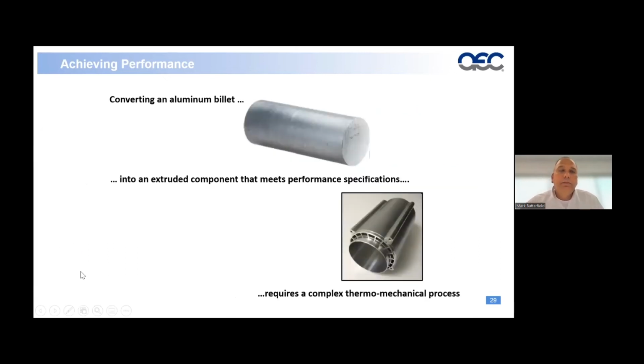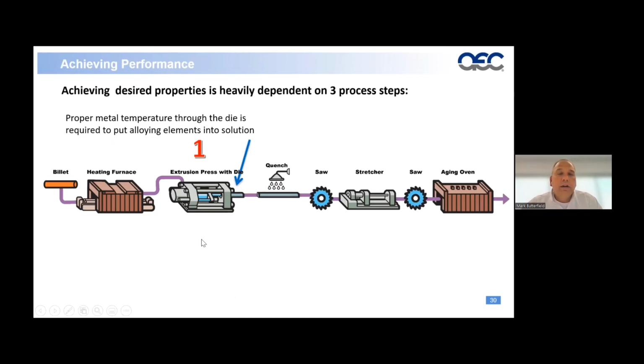Converting aluminum billet into an extruded component that meets performance specification requirements is a complex thermomechanical process. What we do is take a billet through a billet furnace that can be either gas or an infrared oven. Then we put it into a press, with all different size presses and billet diameters. We typically take the cross section of the profile and align that to what's called a reduction ratio, and then we can size a press to that.